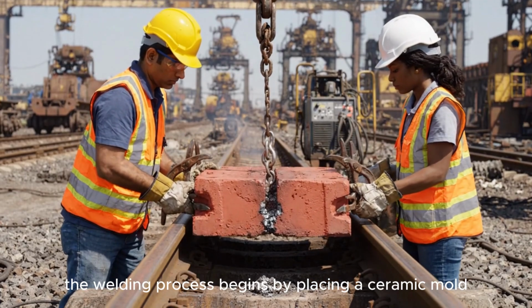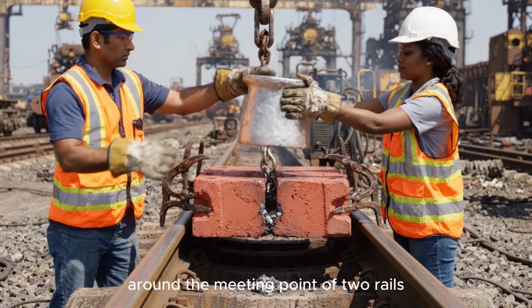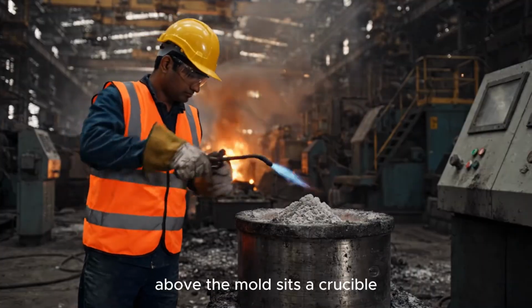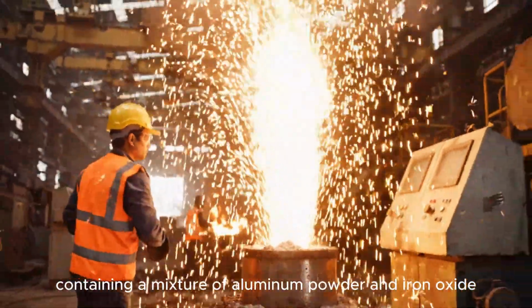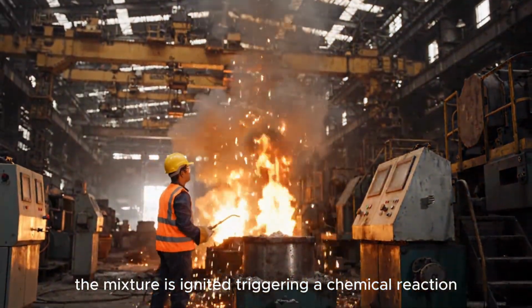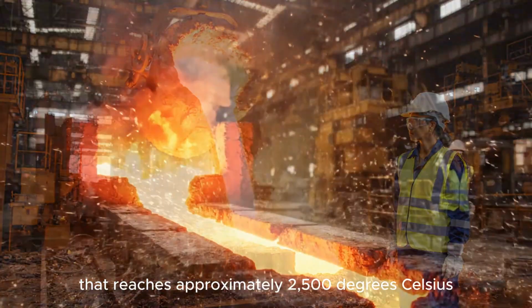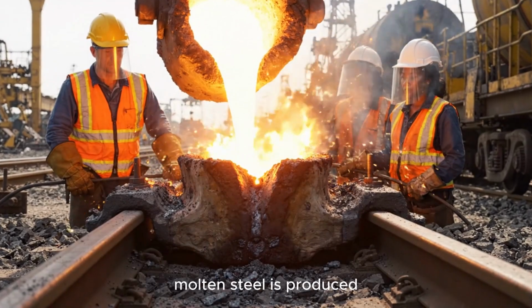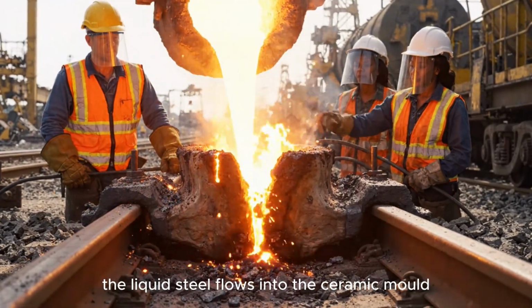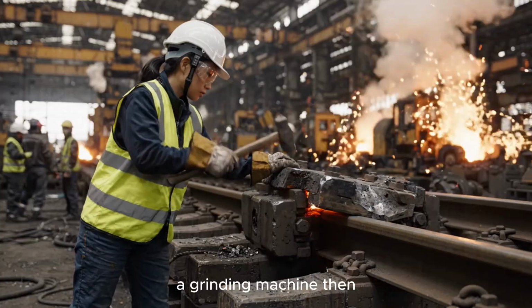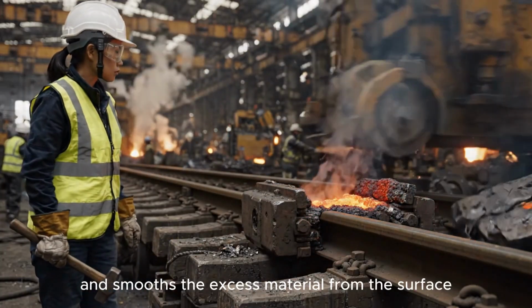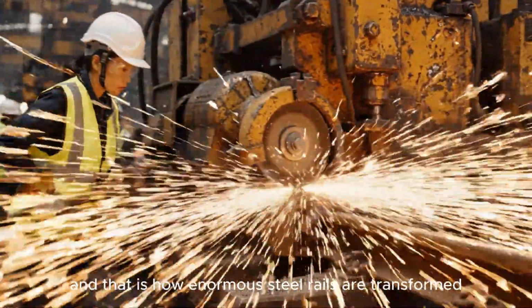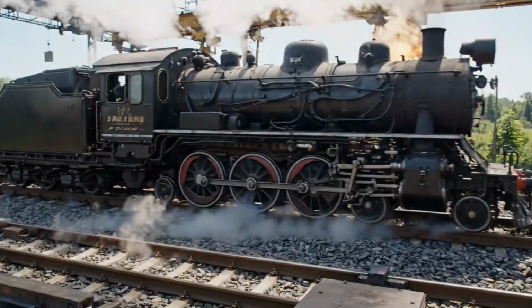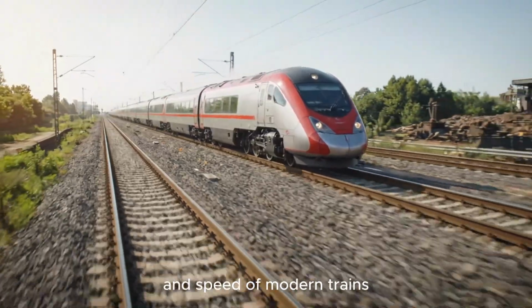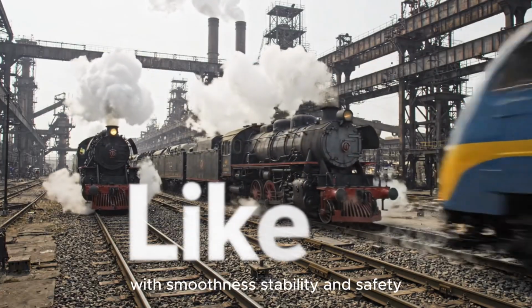The welding process begins by placing a ceramic mold around the meeting point of two rails, leaving a small gap between their ends. Above the mold sits a crucible containing a mixture of aluminum powder and iron oxide. The mixture is ignited, triggering a chemical reaction that reaches approximately 2,500 degrees Celsius within only a few seconds. At that extreme temperature, molten steel is produced. The liquid steel flows into the ceramic mold, filling the gap between the two rails. A grinding machine then removes and smooths the excess material from the surface. And that is how enormous steel rails are transformed into continuous railway lines, capable of carrying the incredible weight and speed of modern trains. With smoothness, stability, and safety.